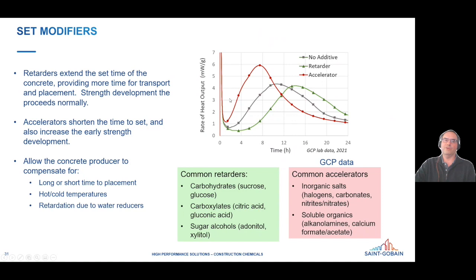So there are a lot of real applications for this. I think I've already mentioned that if you have a long distance to go to get to the job site, you certainly are going to want to use a retarder to extend the times. On the other hand, if you're placing concrete in very cold weather, which slows down the hydration process, you want an accelerator so that it sets more quickly, and so on. You can see that retarders are often things like sucrose and other carbohydrates, whereas accelerators tend to be the inorganic salts. Calcium chloride and calcium nitrate, I think, are two of the most common ones.